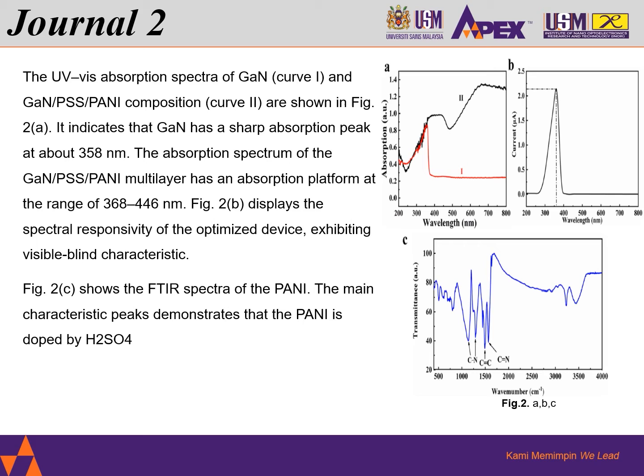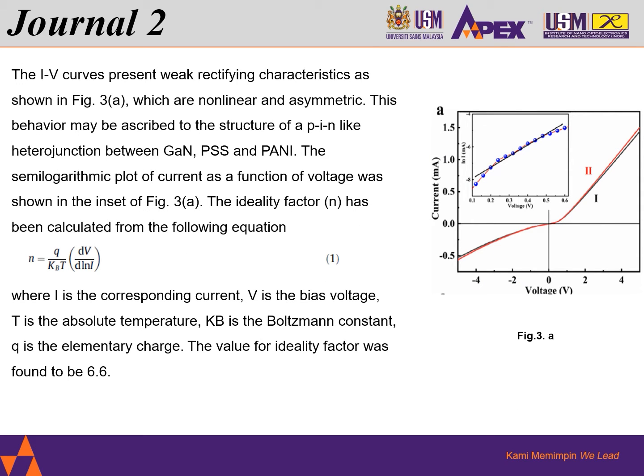Figure 2c shows the FTIR spectra of the PANI. The main characteristic peaks demonstrate that the PANI is doped by H2SO4. Now the IV curves present weak rectifying characteristics as shown in figure 3a, which are nonlinear and asymmetric. This behavior may be ascribed to the structure of a PIN-like heterojunction between GaN, PSS, and PANI.